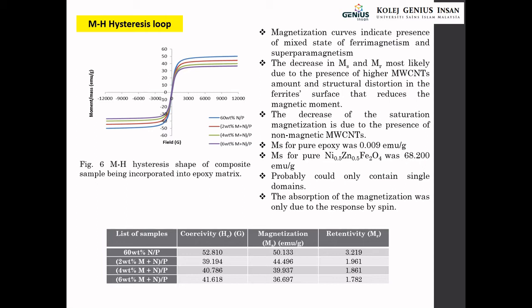As we increase the weight percentages from 2 weight percent until 6 weight percent, the MS value is decreasing. The same goes for the MR value, which is decreasing, and it is most likely due to the presence of a higher multi-wall carbon nanotubes amount and structural distortion in the ferrite surface that reduces the magnetic moment. So the decrease of the saturation magnetization is due to the presence of non-magnetic multi-wall carbon nanotubes.